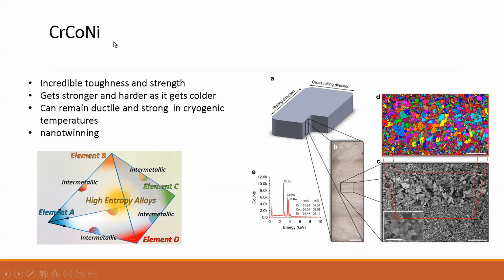However, chromium cobalt nickel belongs to a family of alloys called high entropy or medium entropy alloys, depending on the classification. But the important thing is that these types of alloys are found as near equal distribution of elements in the alloy. So the chromium, cobalt, and nickel are found in near equal amounts in this alloy. And that gives different characteristics and different properties in terms of the crystalline structure of the material.